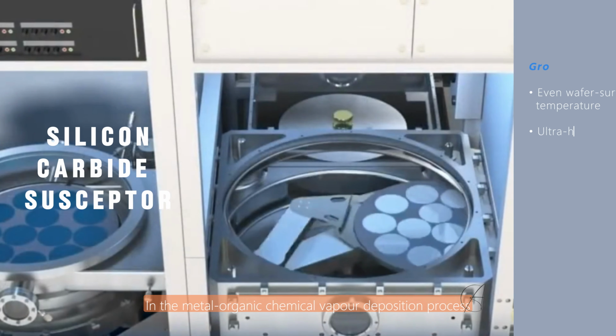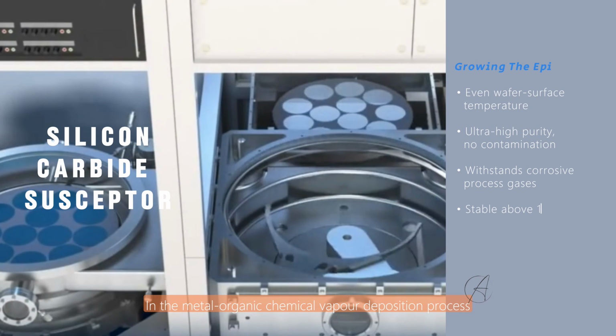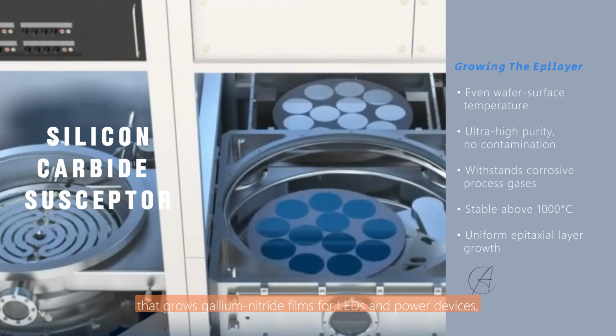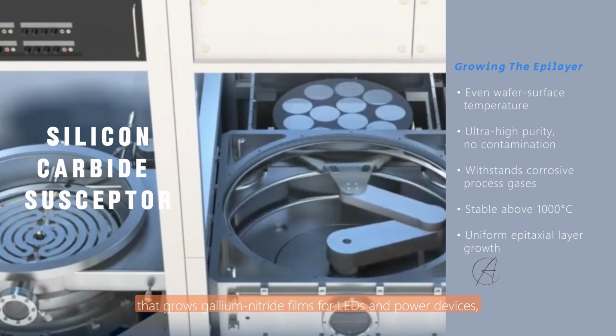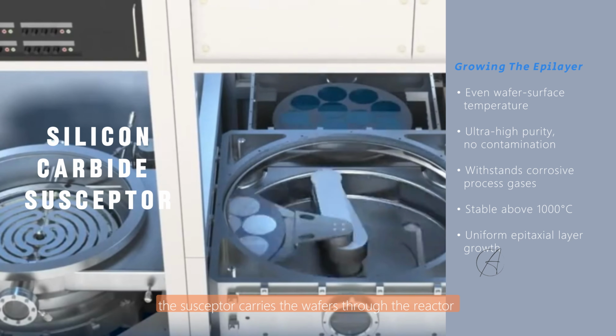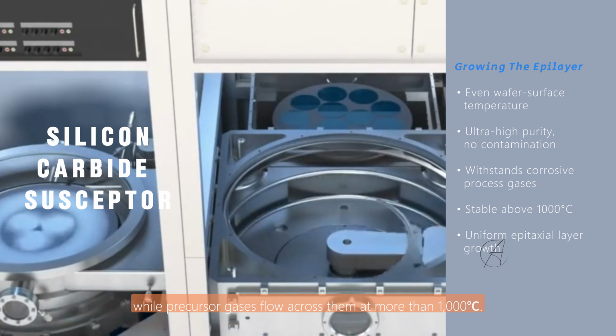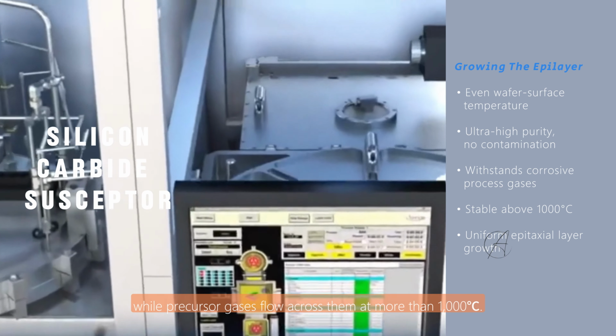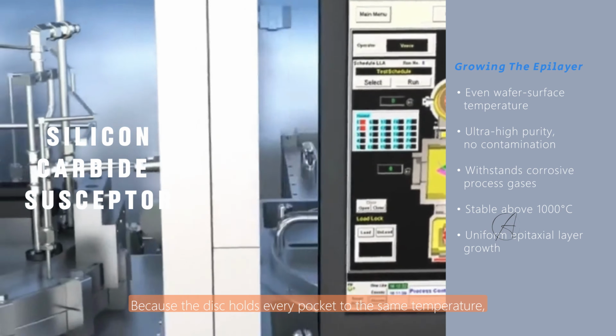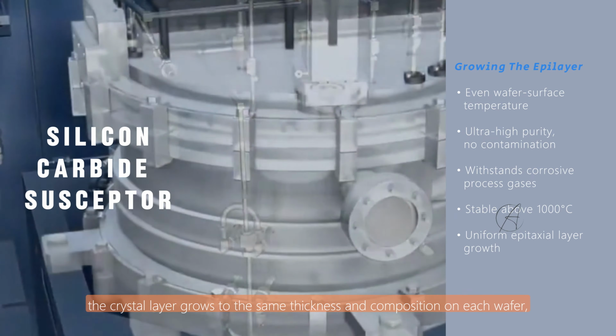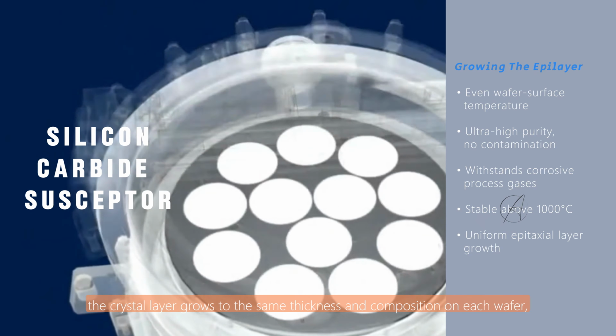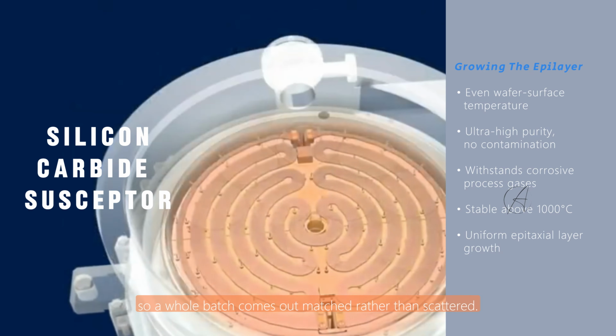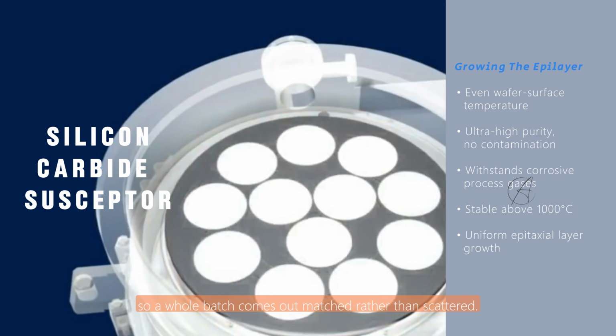In the metal organic chemical vapor deposition process that grows gallium nitride films for LEDs and power devices, the susceptor carries the wafers through the reactor while precursor gases flow across them at more than 1,000 degrees. Because the disc holds every pocket to the same temperature, the crystal layer grows to the same thickness and composition on each wafer, so a whole batch comes out matched rather than scattered.